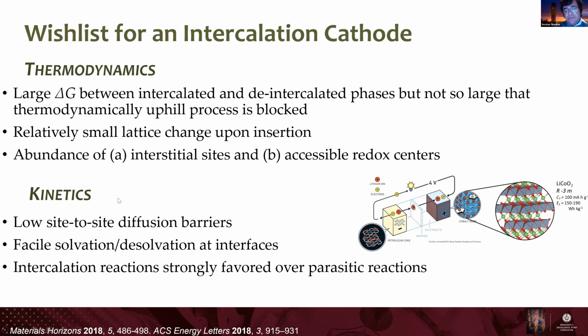Okay, and then in terms of kinetics, the ions are going to have to diffuse within oftentimes crystalline lattices, so site-to-site diffusion barriers have to be low. And it's not enough to just have bulk diffusion. We also have to have the solvation, desolvation processes that happen at interfaces be quite facile. And then intercalation reactions have to be strongly favored over all sorts of other reactions that can also happen, such as conversion reactions or other surface reactions.